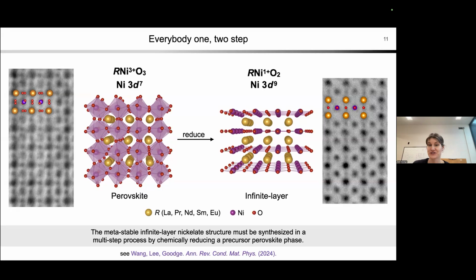That's my opinion. You can see here, for instance, with the annular bright field STEM images that I'm showing you, we can image directly that removal of oxygen as you go from the image on the left, where you see all of those oxygens surrounding every purple nickel ion, to the image on the right, where you can see the oxygens above and below that ion are missing from the structure. So this is great to help the synthesis confirm that it's the correct phase that we're interested in.